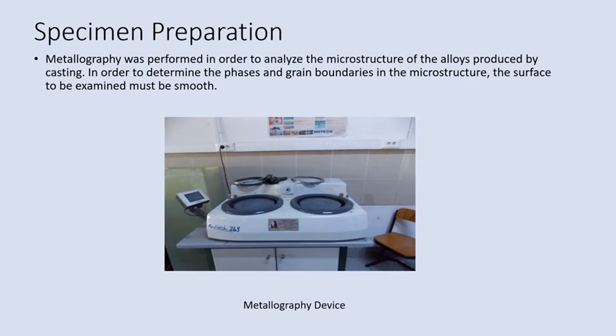After we produce the alloy, we prepare the samples for our tests such as microstructure analysis. To do that, we use metallography, as you can see in the picture below. We determine phases and grain boundaries in the microstructure, and to do that, the surface to be examined must be very smooth.